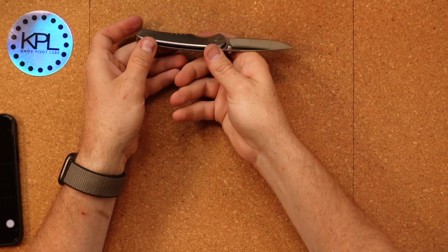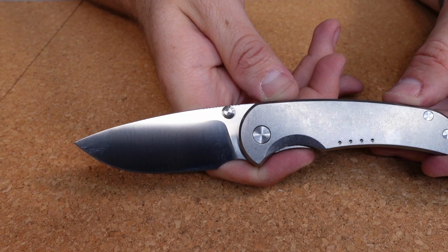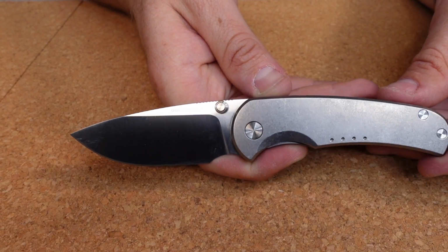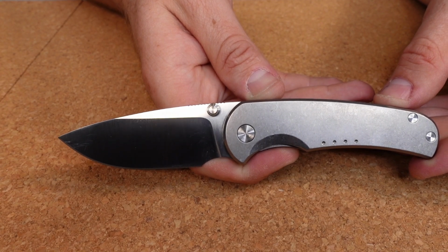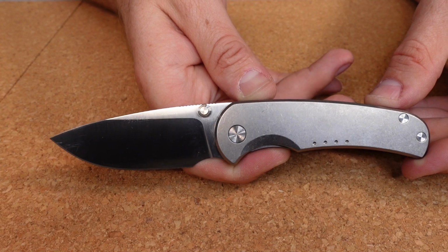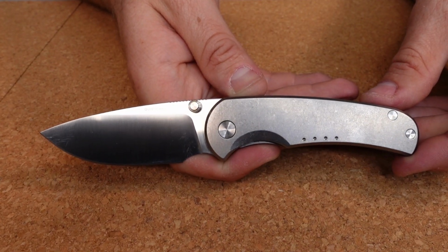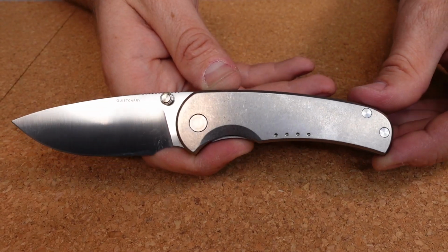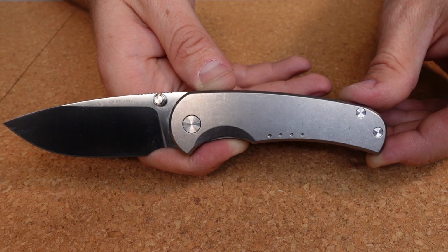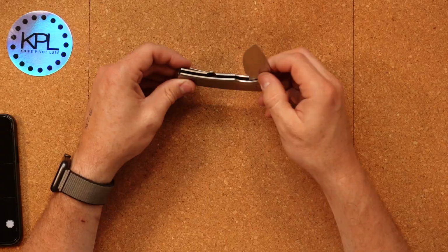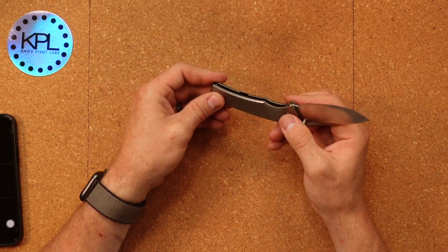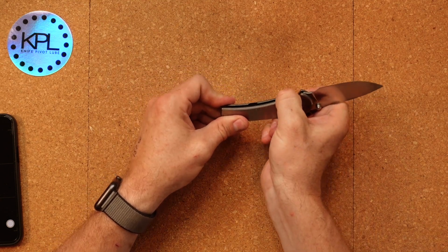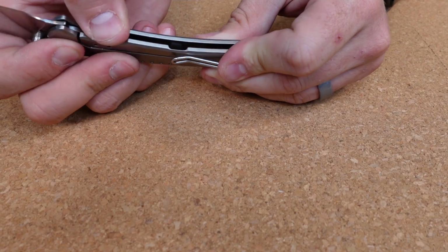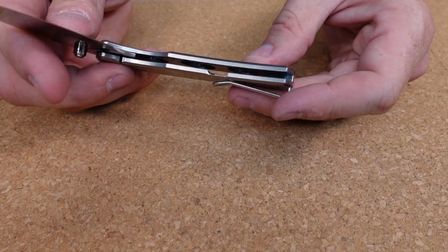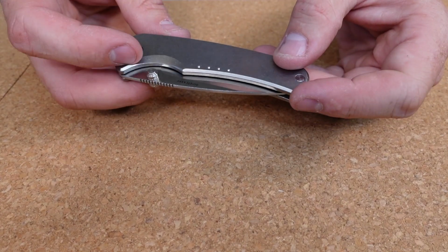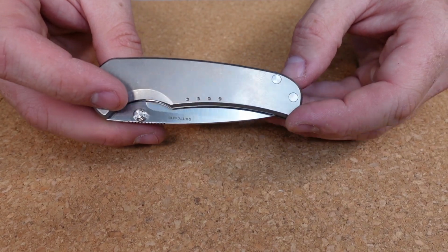Interesting fact about the titanium scales that you have on your knife is that they're probably made out of 6Al4V titanium rather than pure titanium. That means they include about 6% aluminum and 4% vanadium. Those alloying elements help to stabilize the crystal structure within the titanium itself, leading to a mixture of different forms of titanium crystals that gives it additional strength and stability, and also gives it a really good resistance to metal fatigue, meaning that the spring bars on these knives are going to last basically forever. It's almost impossible to wear them out by flexing them over and over again. Titanium makes a very good spring due to its properties. Specifically, the 6Al4V titanium is just really, really good at doing its job in pocket knives.